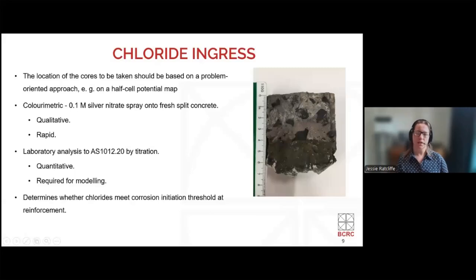We test for chlorides. We take a concrete core sample. The sample's location should be selected based on that problem-oriented approach using the inspection, or the half cell potential map might show you areas where we have a higher chance of corrosion occurring and should be investigated.